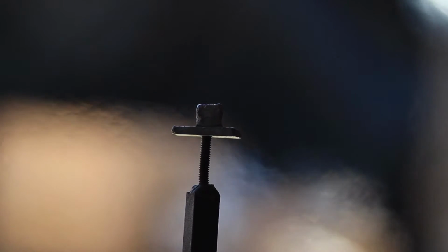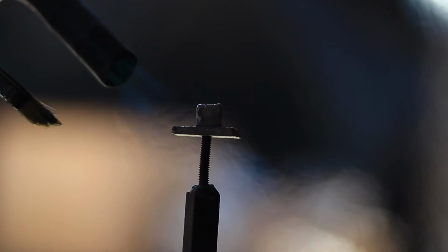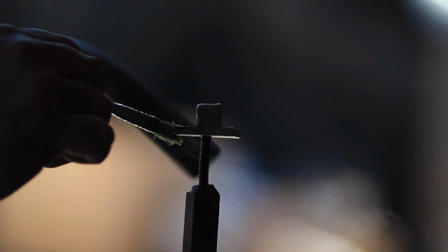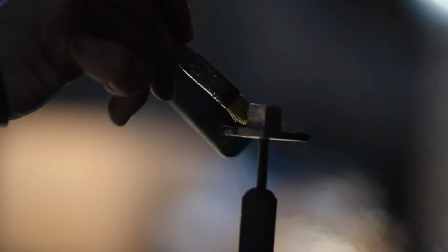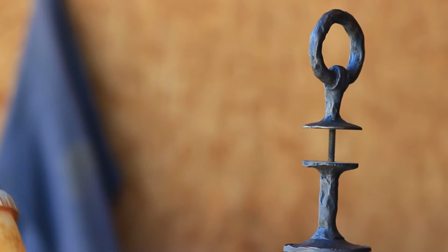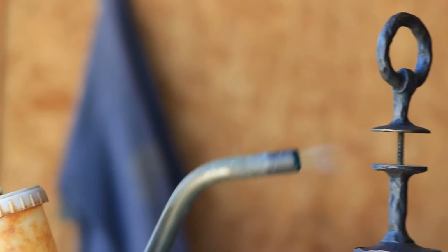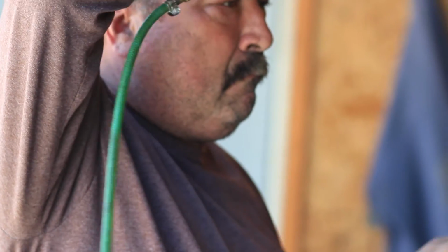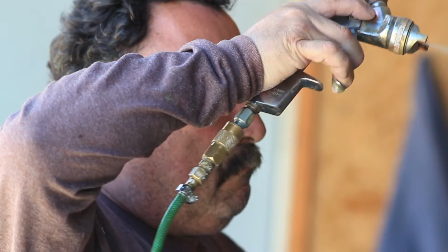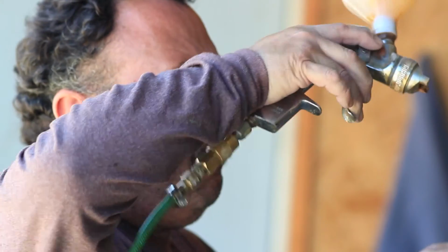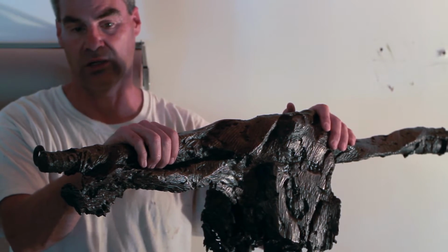This process is done with a torch. I prefer hot patinas. There are two types of patinas, hot or cold. The hot patina is done with a blowtorch and chemicals. For this, we used ferric nitrate. Ferric nitrate turns things to gold. But the longer you work with a product, the higher the temperature, the browner it gets. I wanted this to be gold, but I wanted it to first go brown, so that we got a higher temperature, more chemicals involved in it.